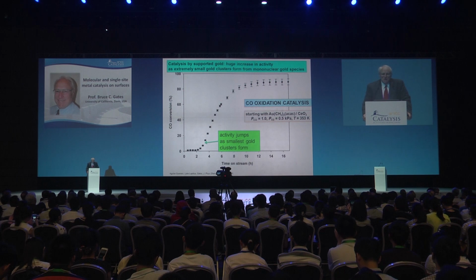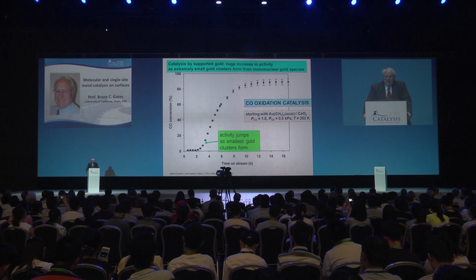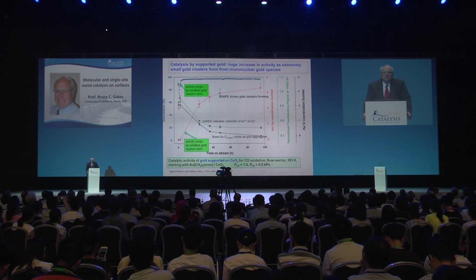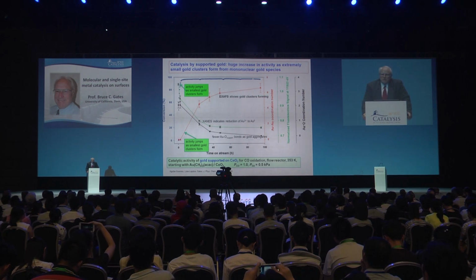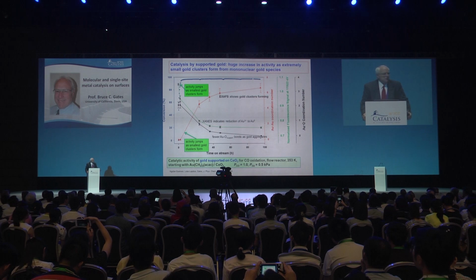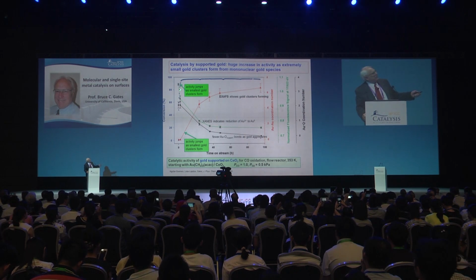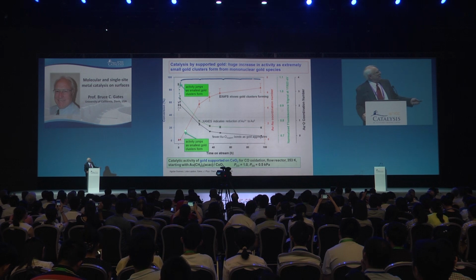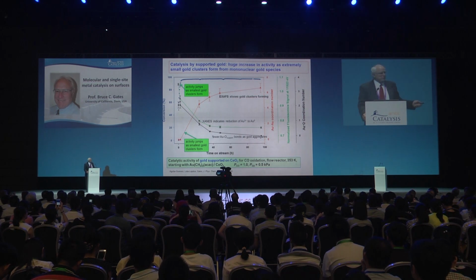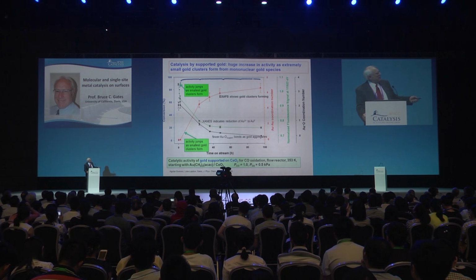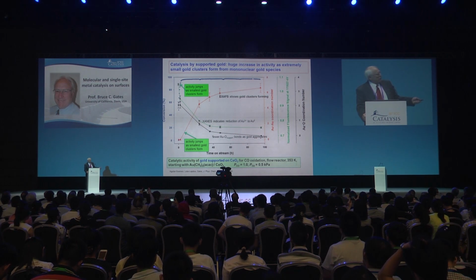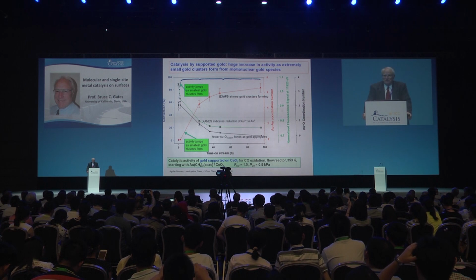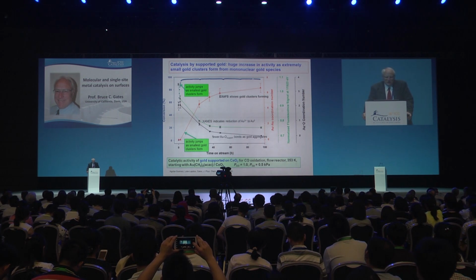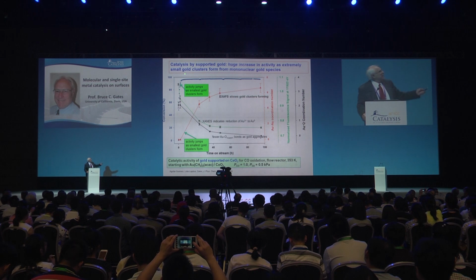But after a short time of operation, the activity of that catalyst increases hugely. What's going on? X-ray absorption spectroscopy of the functioning catalyst tells us: as the activity increases rapidly, the XAFS gold-gold contribution increases rapidly, and by the time the gold-gold average coordination number is only about 1 - which on average means dimers - the catalytic activity is way up.